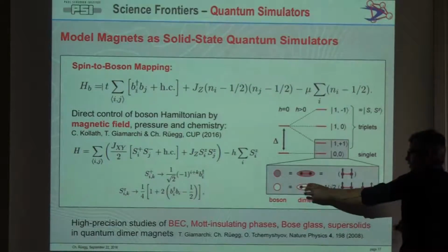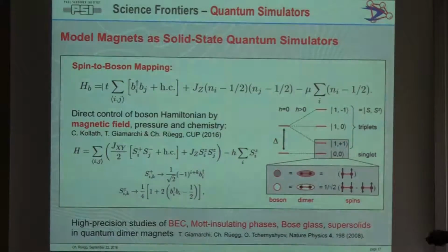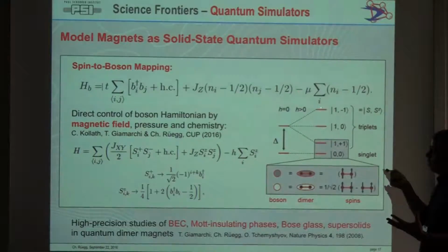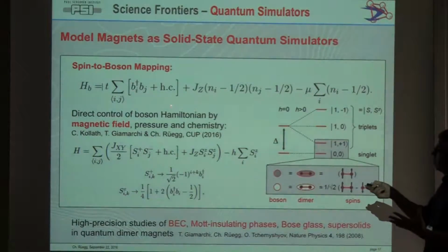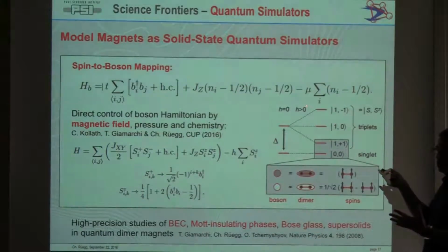So I tell you that you have to find dimers, and then you have interesting materials which form one-dimensional structures, two-dimensional structures, and so on. And in the end, you can map the spin problem onto a quasi-particle bosonic Hamiltonian, where essentially you have a hopping term, an interaction term, and the chemical potential.